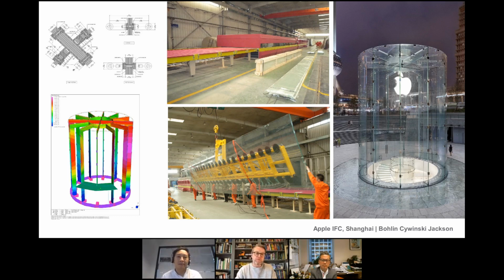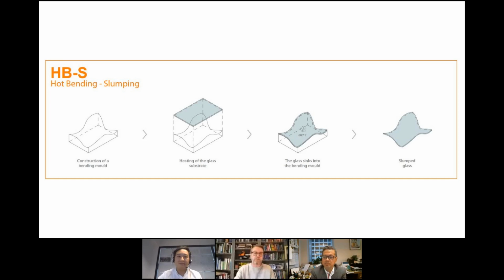The challenge with thermally tempering glass is the radius. The machines can only bend to a certain diameter, and that wasn't tight enough for us to be able to get a semicircle. So we were very much faced with the idea of looking more deeply at hot bending and slumping, which is essentially taking the mold that you want to form the glass, then heating the glass over that mold, letting it settle into the mold, and then cooling it at a controlled rate such that it was annealed, leaving you